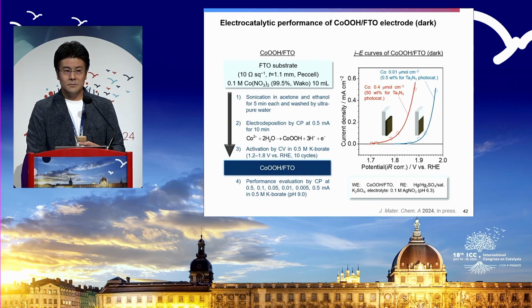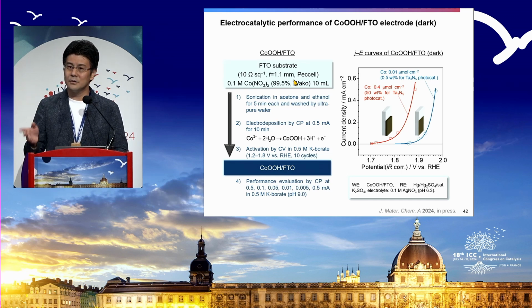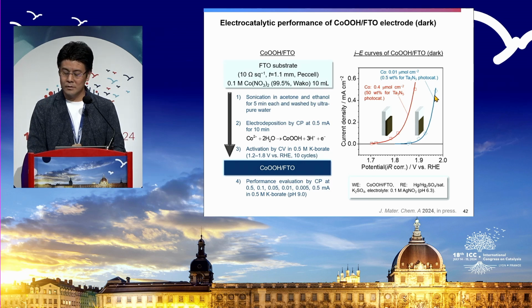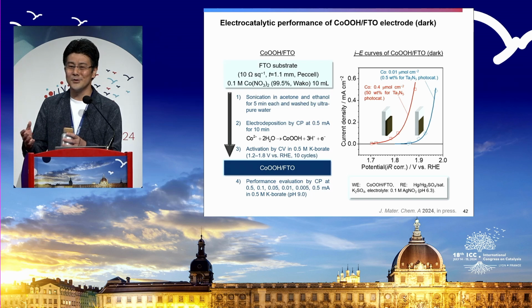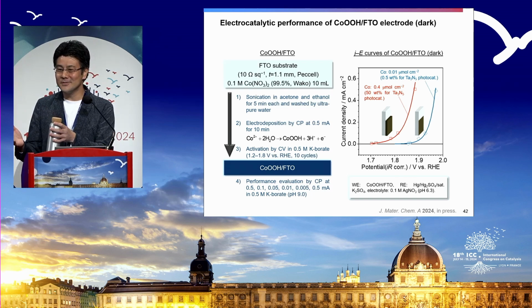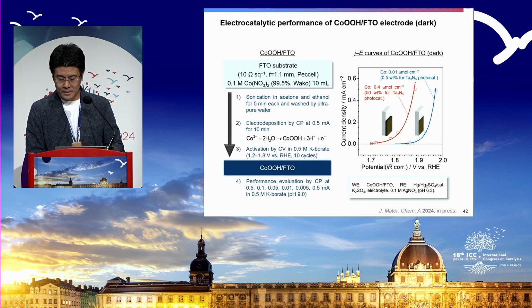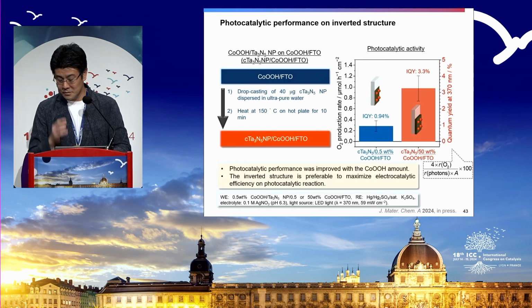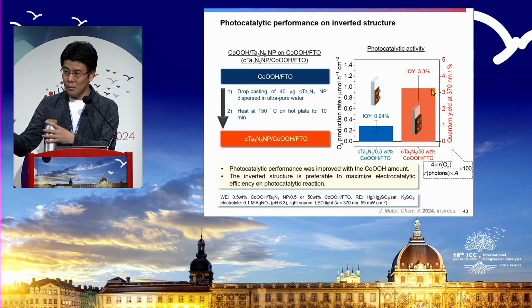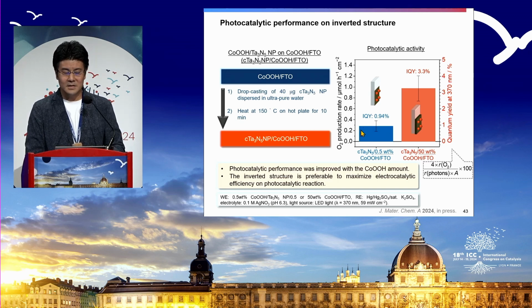Okay, so this is what we did. First we make 2 electrodes, with completely different amounts of cobalt. Low quantity of cobalt is here, and much more cobalt. This is equivalent to 50 weight% of tantalum nitride. So you would almost cover the entire tantalum nitride, right? It becomes almost black. But then we have this IV curve, right? And let's see what happens if you put tantalum nitride on top of it. In fact, long story short, you needed to have much more oxygen evolution catalyst. So this is more cobalt that was on the electrode. And here is much less.